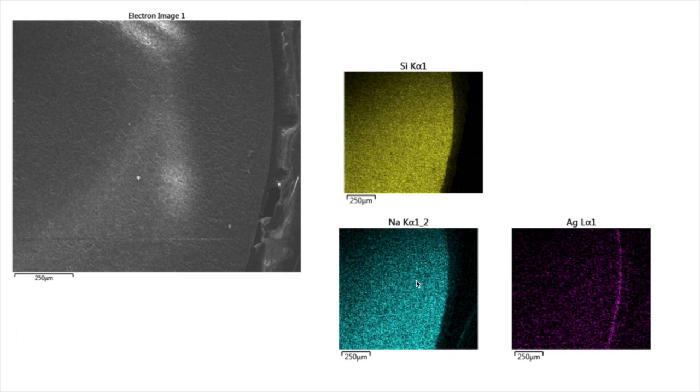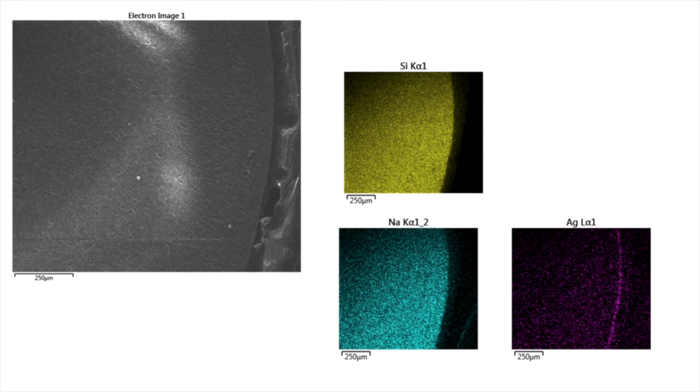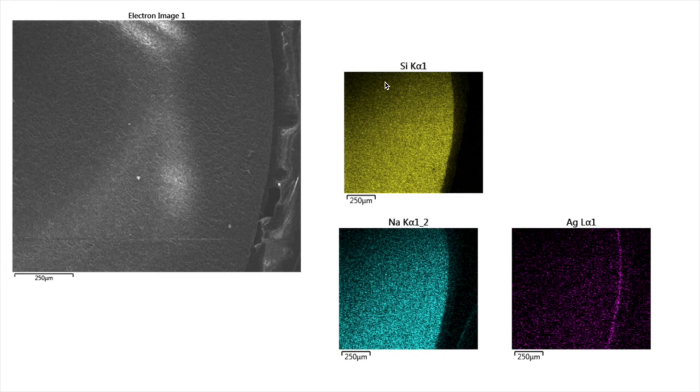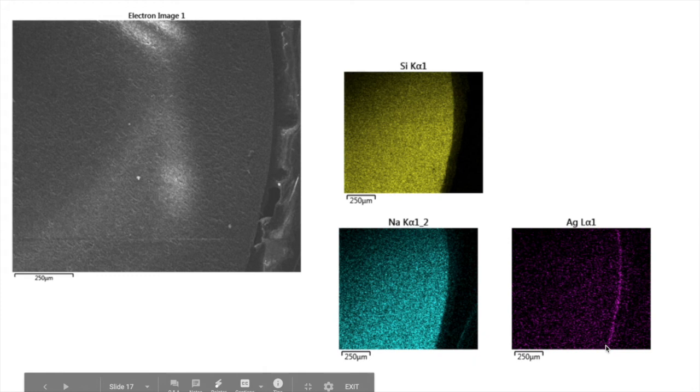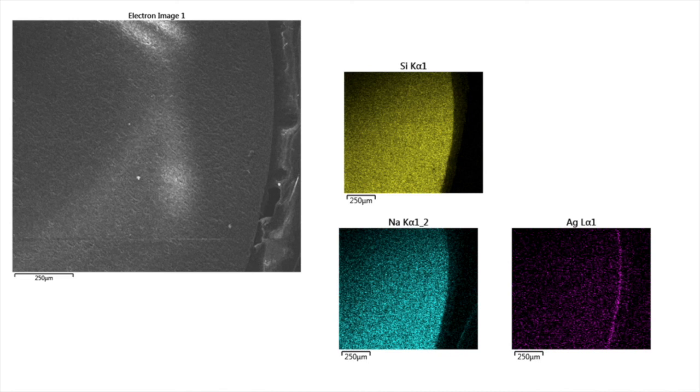Same thing with sodium. Whenever you see one of these turquoise colors, that's where a sodium K alpha 1, 2 is appearing. And then same thing for silver. So the idea here is that this EDS map allows us to map the various elements in this material. And so you see that throughout the whole glass rod, silicon is fairly uniform. Same thing for sodium. However, silver, just like you saw in the previous line scan, right at the edge, the silver signal is the highest on the edge, and then it's very low in the interior. So we have a much larger silver signal at the edge than we do in the interior.